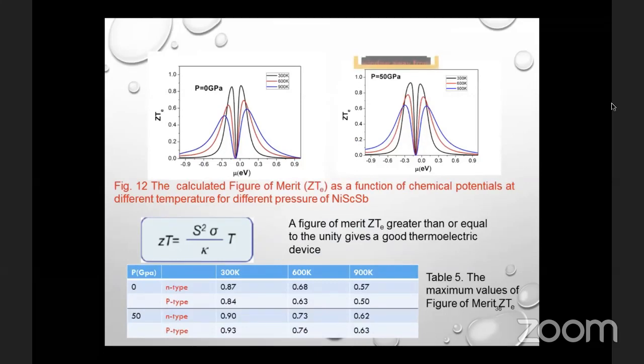From this figure, we notice that the two pressure materials exhibit the same behavior. The predicted upper bound for the figure of merit is about 0.9 at room temperature, which means that both compounds are good thermoelectric devices. As you see in Table 5, the ZT parameter at constant pressure decreases with temperature, but at constant temperature, this parameter increases with pressure. At room temperature, the greatest value of ZT is obtained for 50 GPa pressure and is very close to 1.